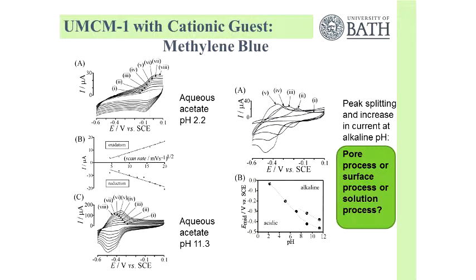This is what we see with the MOF. The behavior really follows the solution processes. In acidic conditions, one nice signal. In alkaline, two split signals. This is shown at pH 2, 7 and 12. It's going really from one MOF signal and it splits into two. All of this really looks like a solution experiment. It follows this kind of pattern where the signal splits at about pH 8.